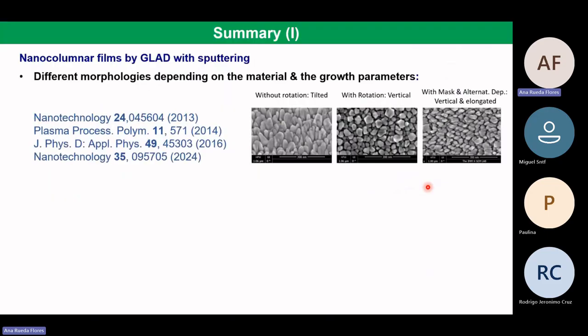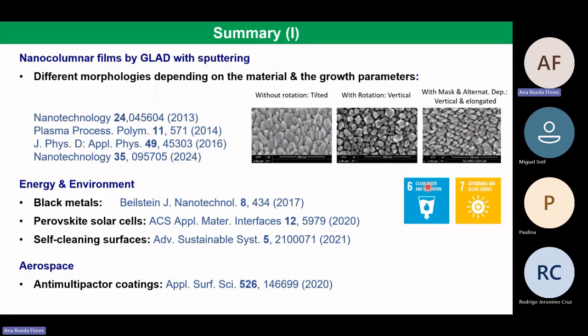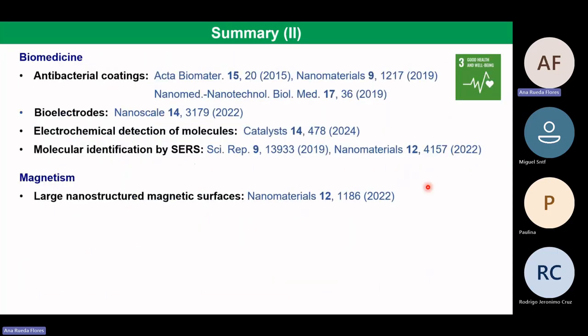Let me just summarize that with glancing angle deposition with sputtering, we can fabricate these nanocolumnar thin films with different morphology depending on the material and the growth parameters, and that we have developed applications in energy and environment, for the aerospace industry, for biomedicine, and for magnetism.